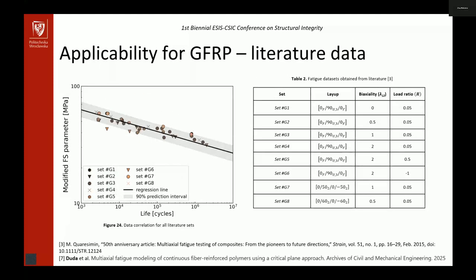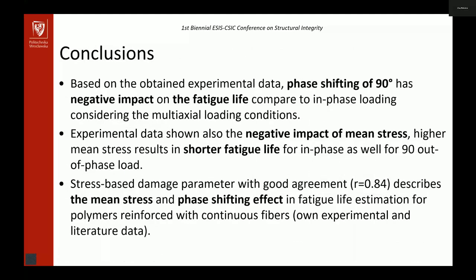Another thing is the applicability to other materials. It's a pretty similar material, since the damage mechanism should be the same. However, the stiffness of glass fiber reinforced polymer is lower than that of carbon fiber, so I took different data from the literature. For the layup configuration, you can have a look here, with different biaxiality load ratios, and that's the correlation for our damage parameter. So let's move to the conclusions.